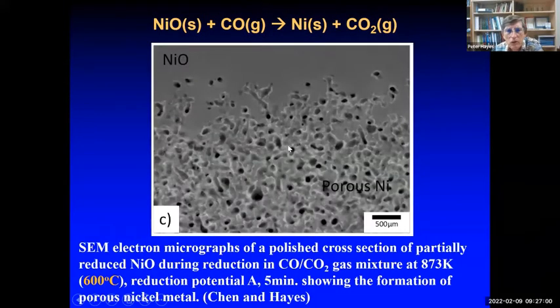If we look closely at that interface, you can see how those pores are created. Essentially, spontaneous tunnels are appearing in the surface. So instead of having a nice flat nickel oxide surface as we started, it's become irregular, and these tunnels are actually burrowing their way into the nickel oxide, and the gas is coming from the outer surface of the particle through these connected pores, and you can see there are some connections here. These connections go all the way to the surface, and so we have gas diffusion through these pores.